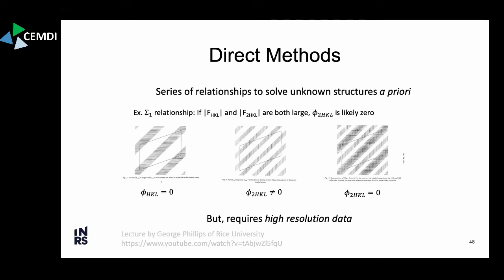And this is because what you're looking at is rule of thumb relationships between pairs of reflections in reciprocal space and the structure factors. So what I showed here is just one of these rules of thumb, and then there's a whole bunch of different comparisons that you can do to try to get likely values for the phase. But if you have structure factors for a given HKL and 2 times HKL, in other words, if I have the 100 and the 200 structure factors, and they're both large, then most likely the phase for the 200 reflection is 0.